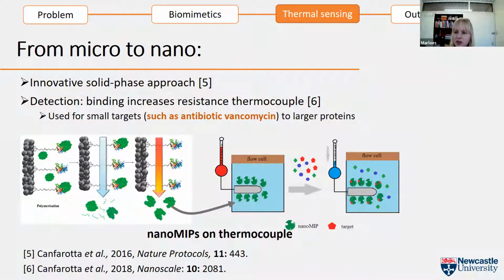These nanoparticles, which at the moment are somewhere between 50 and 100 nanometers, but there's a drive to go even smaller, are water soluble, so we can directly coat them onto surfaces. We've used approaches from simple dip coating to drop casting, and we have these nanoparticles for small molecules, such as the antibiotic vancomycin I mentioned. We have them for proteins, but you will also see later on, I have a little slide on how we use them for viruses and bacteria as well.